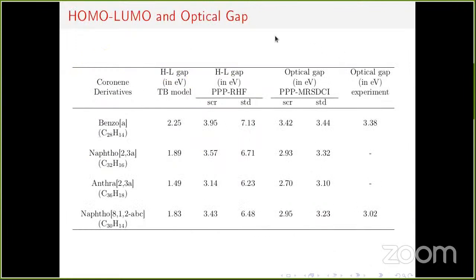Okay, so let us compare. It was a much bigger paper and I have only 15 minutes here, so let me just briefly summarize the results which we obtained at various levels of theory on the optical gap. You can see that using the tight binding model, we get very low values for the gap, and they are likely to be wrong because for a couple of molecules we have experimental results, and they are much less than the experiments, so they are likely to be wrong for the other two also.